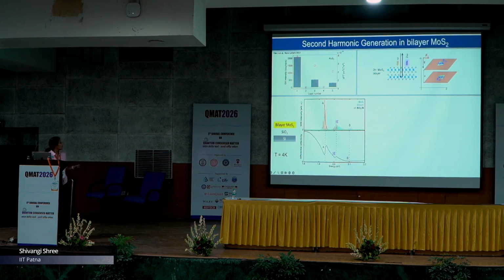do not see it. So, in this experiment, this is again the usual reflection measurement on homobilayer MoS2 directly grown on silicon oxide. So, we have the A exciton, B exciton, interlayer exciton. Now, to collect this second harmonic signal, we tuned the laser energy across these exciton resonances. So, each spectrum here is taken at a different laser excitation energy. Here what we see is the enhancement of second harmonic when we hit the exciton resonance.